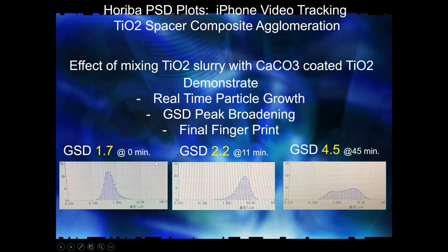Now, this type of thing happens in paint making, and you don't realize it and you can't track it, but you can if you have a Horiba. So what you do is you add your pigment into the water and then you add your resin to it and track it. And I like using the iPhone because I can zip forward or backwards with a little thumbnail on the bottom there, and I can watch it move.